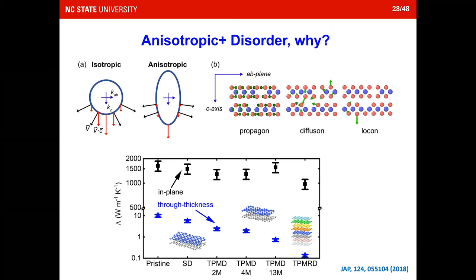Why can anisotropic plus disorder actually achieve even lower thermal conductivity? We're trying to understand that. From a simple perspective, for phonon theories, we know that if you have isotropic and anisotropic materials, anisotropic materials probably would have fewer phonon modes or fewer phonons populated in particular directions. That's one reason. Another reason is that you probably have smaller projections of group velocity in that particular direction. So that provides a smaller propagation speed in the material in certain directions.